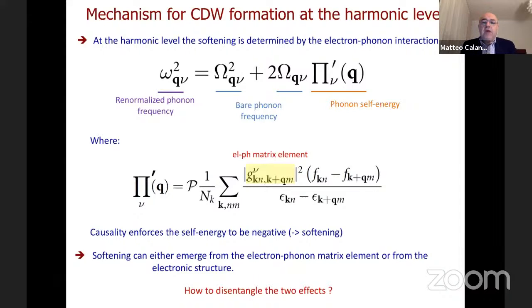But every time you have a second order phase transition, anharmonicity is very important. What does a second order phase transition mean? It means that the lattice becomes soft. If you have a soft mode, then the second derivative of the energy is very small, so your potential is extremely flat. And if the potential is very flat, the anharmonic corrections become important. If the second derivative is almost zero, then the third and fourth derivatives become important. So every time you have a second order transition involving the lattice, anharmonicity plays an important role. The magnitude of this role is more difficult to evaluate, but you can expect that it plays an important role. Okay, thank you.